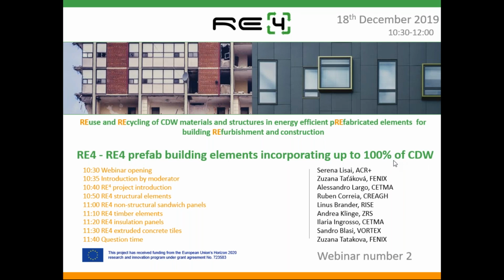Okay, thank you, Serena, for that question. To answer quite rapidly, both are very good because they are based on high levels of construction and demolition waste in the concrete. But the extra benefit of the non-structural panel is that the carbon fiber reinforcement is in itself lighter than the steel reinforcement. And this, together with the fact that it's now also possible to make the panel much thinner, so we make it half the thickness of the ordinary outer layer, also reduces the weight. So in total, reducing the weight with maybe 20% of the full sandwich panel.